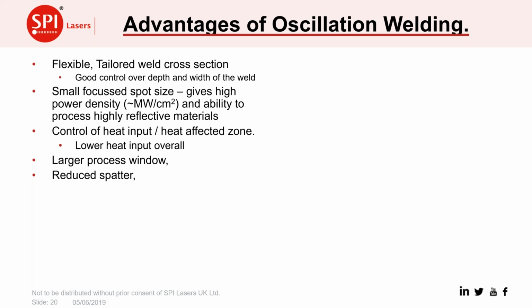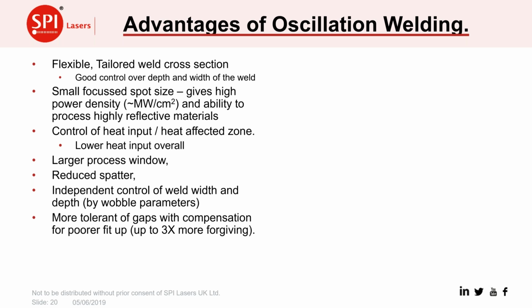We can often produce welds in, for instance, copper with very much reduced spatter because we are able to control the heat input into the weld and into the melt pool. And we're now able to independently control the width and the depth of the weld pool and therefore of the finished weld. One thing that we've also found, which is very useful, is that it's very tolerant of gaps. We can compensate for poor fit up in processing. For those who are familiar with welding in standard ways, this really helps in coping with parts where the manufacturing hasn't been quite as good as it could be.